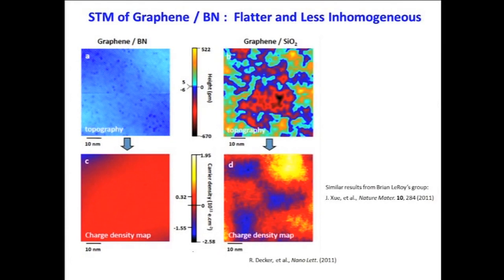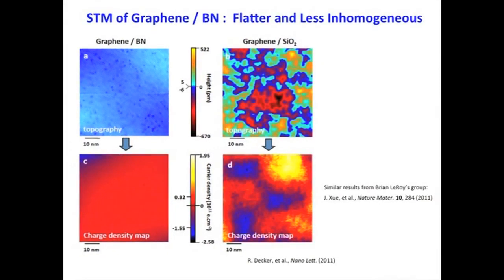And so this helps solve one of our problems, which is this inhomogeneity problem. Here we compare graphene on boron nitride to graphene on silicon oxide. This is the topography comparison, and you can see that graphene on boron nitride is orders of magnitude more flat. And also down here, we compare the charge inhomogeneity for graphene on boron nitride compared to graphene on silicon oxide. You can just see from the color scale that graphene on boron nitride is much more homogeneous. So that's really great for us. That solves one of our problems.